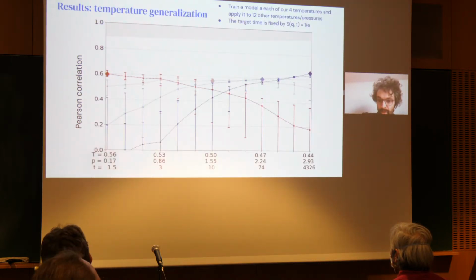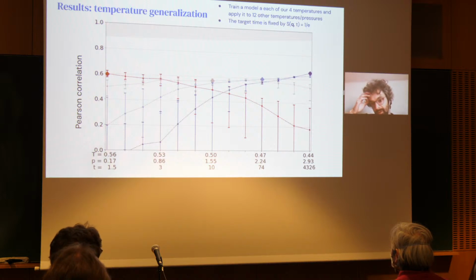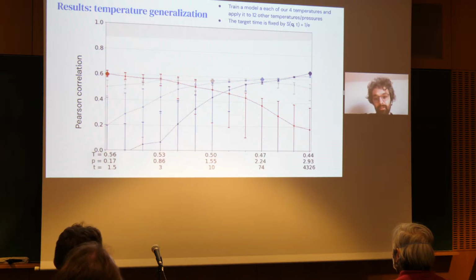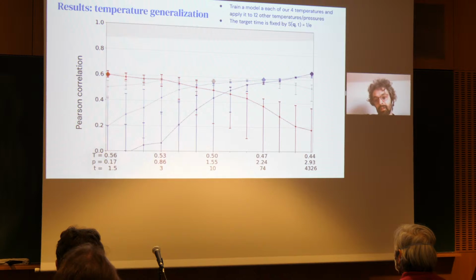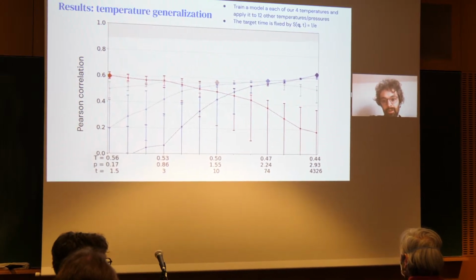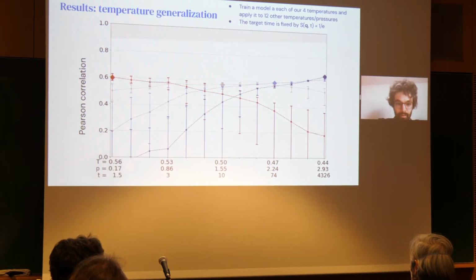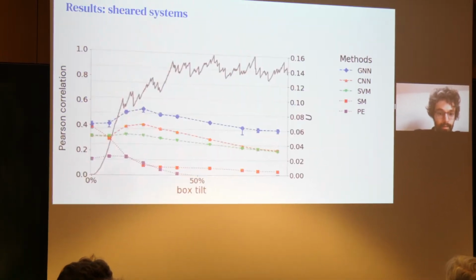We looked at temperature generalization. So can we train a model at a given temperature, and how does it degrade when you go to other temperatures? And I think we found the behavior that you expect, that you have a nice degradation as you change the temperature. So you do well on temperatures near yours, and then you degrade. What was interesting is that the network that we trained at a slightly higher temperature, so 0.47, could extrapolate very well to lower temperatures. And that's of course interesting from a practical perspective, because evaluating the network is typically much cheaper than training it, and you need far less data. So if you can train models in cheaper conditions and they extrapolate to the harder ones, the ones harder to simulate, that could be quite interesting in practice.